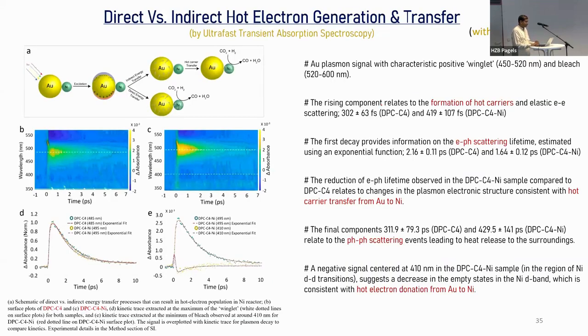We also tried to prove the electron transfer. We collaborated with Professor Jacinto Sa for the ultrafast transient absorption spectroscopy, which I'm not an expert in, but we just wanted to show that there is electron transfer from gold to nickel. And this particular bleach indicates that electrons are moving to the nickel, feeding the nickel states, and that's why there is no more excitation in the nickel, and that's why you get a bleach in there. And that's a basic understanding of this data.